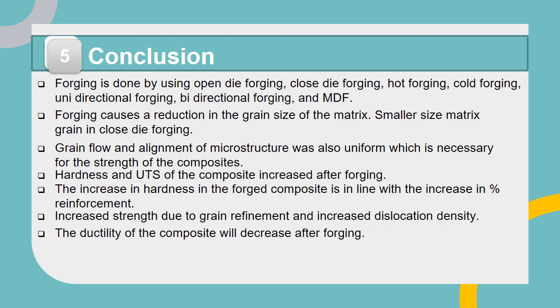Hardness and UTS of the composite increase after forging. The increase in hardness in the forged composite is in line with the increase in percentage of reinforcement. Increased strength is due to grain refinement and increased dislocation density. The ductility of the composite will decrease after forging.